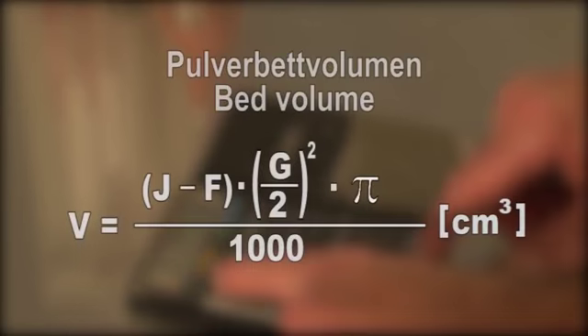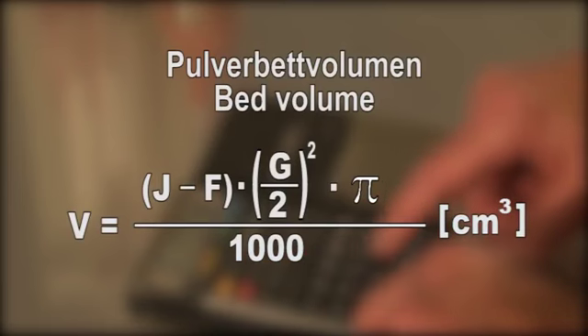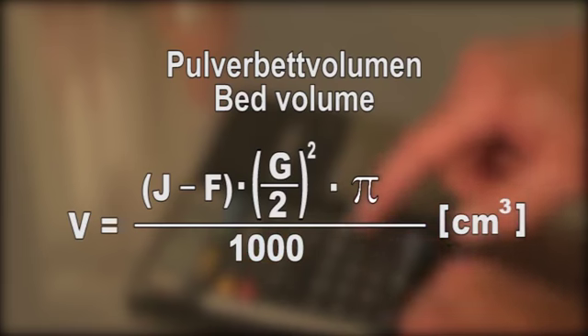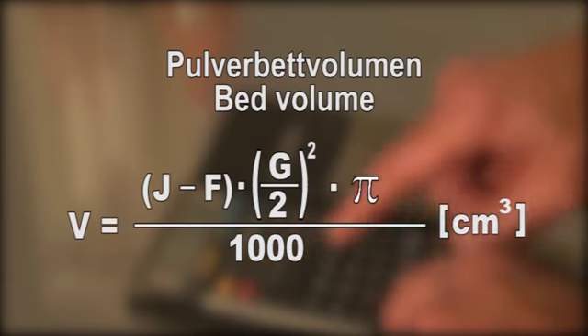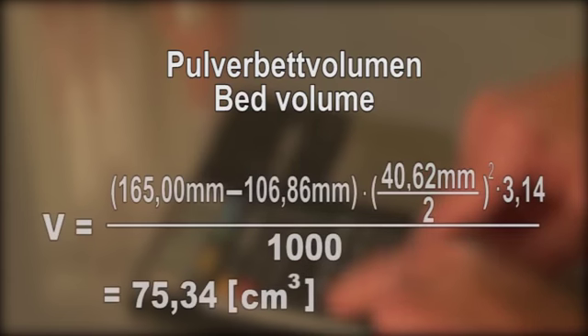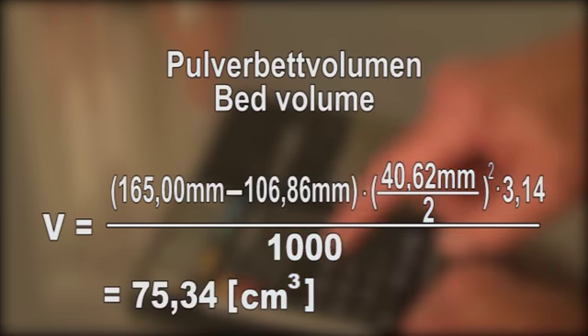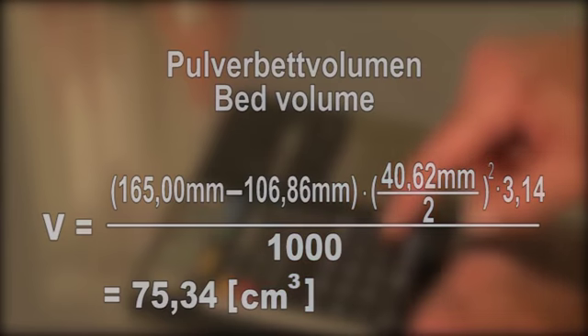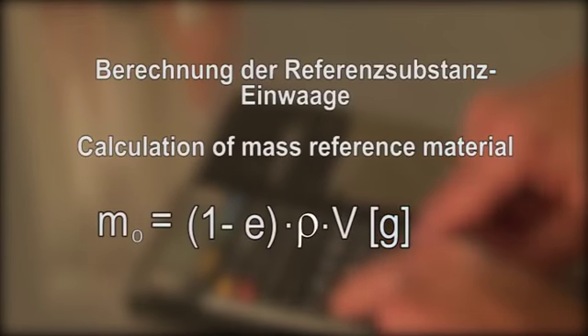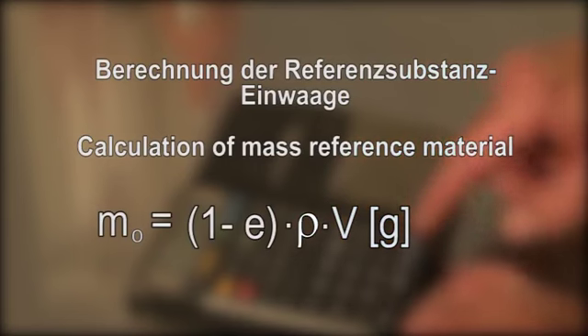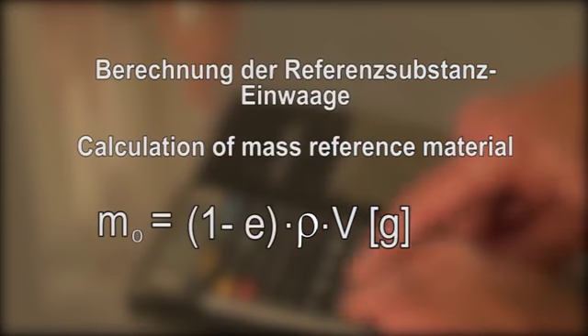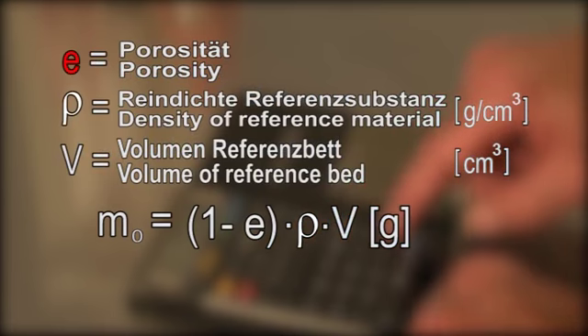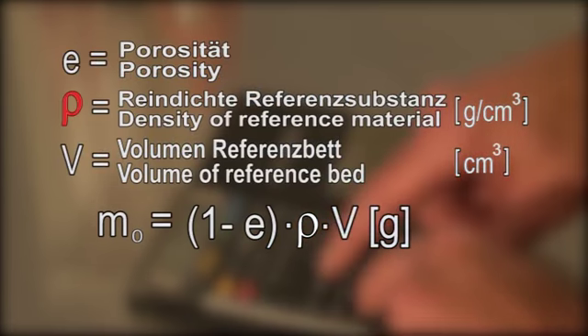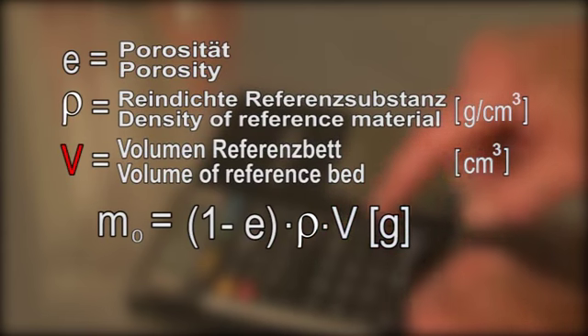Now, the powder bed volume can be mathematically calculated from equation 1, which includes the inner dimensions J of the cell, the plunger length, F, and the cell diameter, G. With the powder bed volume V and the known and adopted data of the reference substance, the mass M0 of the bed is exactly weighed out using equation 2 to 0.01 grams. In this, E represents the porosity of the reference substance, ρ equals the density of the reference substance, and V the powder bed volume.